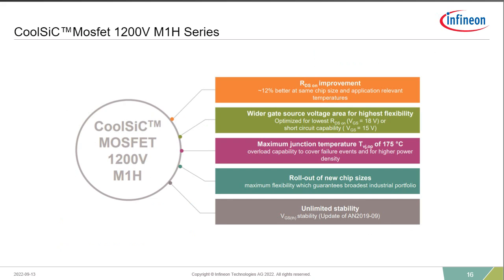So Infineon is now in our essentially generation 1.5 devices, what we call our M1H, our first series of devices, which was from a discrete perspective listed as the M1 series. That was a 45 milliohm device. But then very quickly we released the M1H series. And what we were able to do is improve the cell structure of the silicon carbide MOSFET and get about a 12% better RDS(on) specification based on chip size.